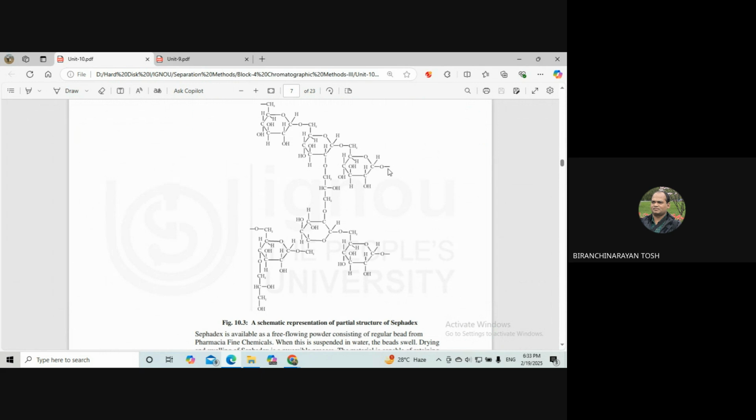The microorganism that is used for fermentation is Leuconostoc mesenteroides strain NRRL B-512. The native dextran has high molecular mass and a wide mass distribution, like 10 to 300 times 10 to the power 6 Dalton. The raw material is first purified, partly hydrolyzed, then finally fractionated by ethanol precipitation to give a product of suitable average mass and narrow mass distribution.